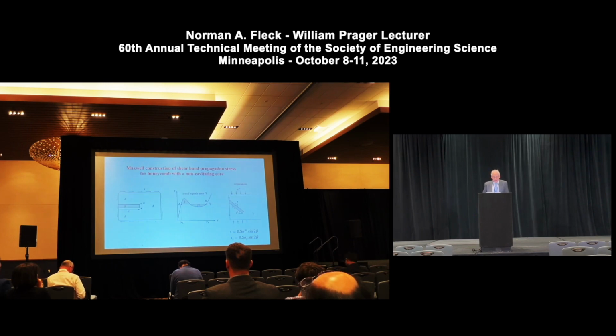So if we take an idealized case of saying that the band is a shear band, so let's take the case of thinking of the honeycomb subjected to shear and evaluate its shear stress strain response. We will see in a second that the response is of this type, where you get a softening and a hardening. You can calculate the so-called Maxwell propagation stress as a horizontal line, where the area above it and below it are the same. This would be the shear stress that's needed to take you from an unlocked initial undeformed state to a fully deformed state, and is the propagation stress that's required in order to propagate this shear band along its length or indeed laterally.